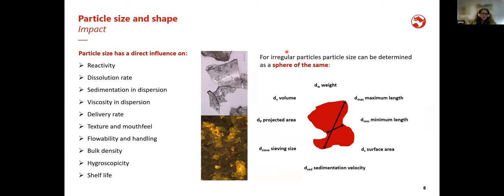Particle size has a direct influence on reactivity, shelf life, and hygroscopicity, because it is directly related to the free surface area. It influences the dissolution rate in combination with shape and microstructure, and is very important for sedimentation in dispersions — for example, in pharmaceutical products where the active must stay homogeneously dispersed. Viscosity in dispersion increases with smaller particles. The delivery rate is also affected — smaller particles give faster delivery. Some retard formulations use a range of particle sizes: small ones for direct delivery, larger ones for delayed delivery.